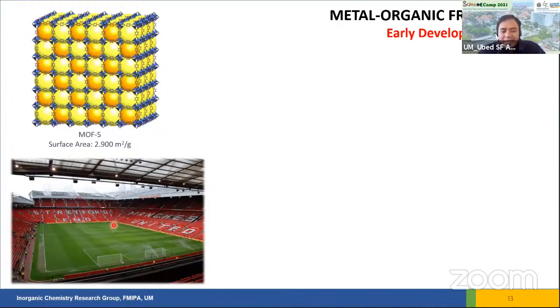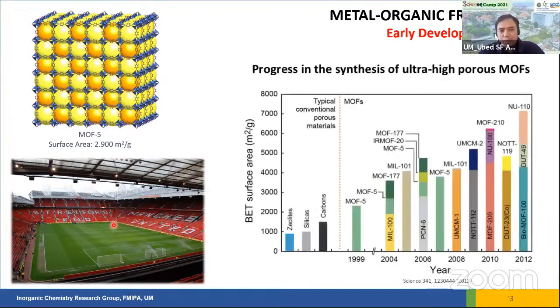So in the early development, scientists tried to break the record of the highest surface area of MOFs. For example, here you can see zeolites from nature are around 800 square meters per gram. Silicas are around 1,000 square meters per gram. Porous carbon, for example, broke the record at around 1,500 square meters per gram. MOF-5 itself is 2,900. This was in the year 2004.